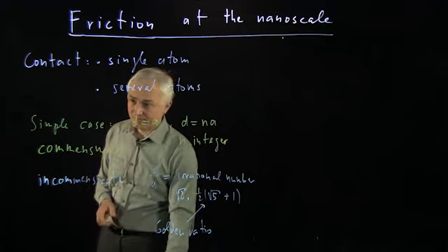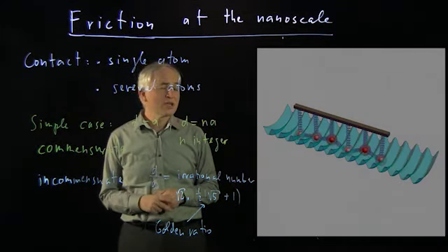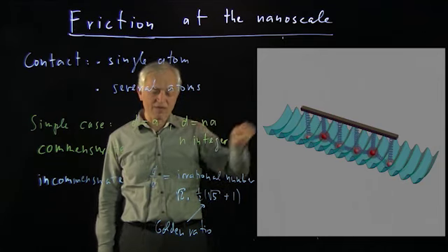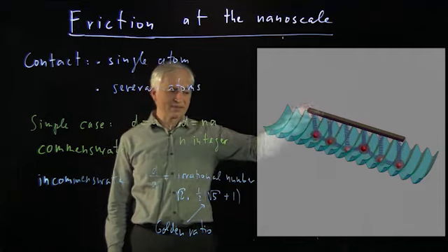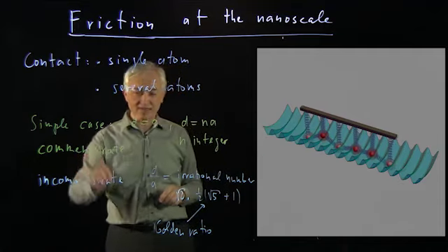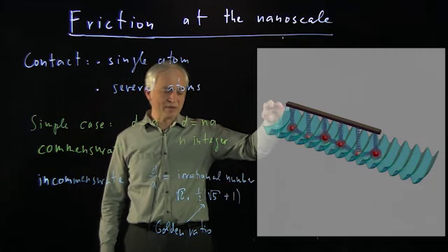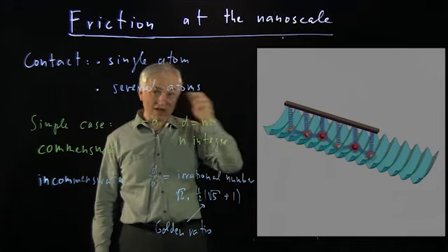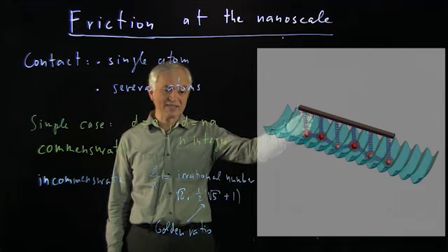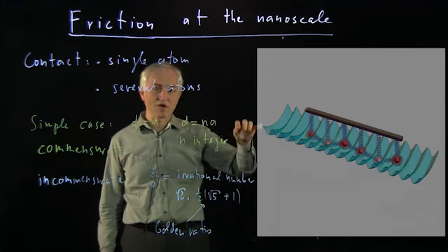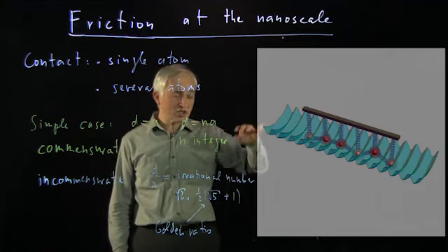So you can see here that in the case of an incommensurate ratio, the behavior of the transport, the behavior of the motion of the object changes dramatically. Instead of all the atoms sticking and slipping together like we had in the commensurate case, now the atoms move one by one. Basically, the first atom moves over the barrier, the spring stretches, which facilitates the motion of the next atom over the barrier, the next atom, and so on. So these atom chains move like a caterpillar. They essentially move one by one.